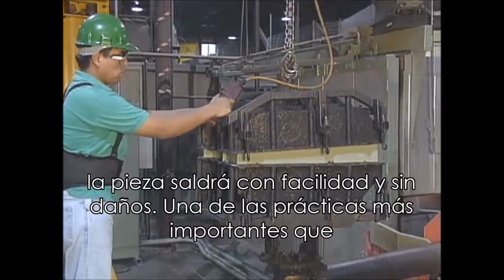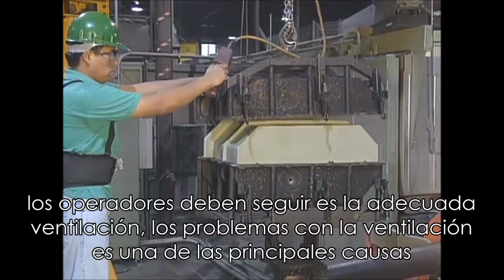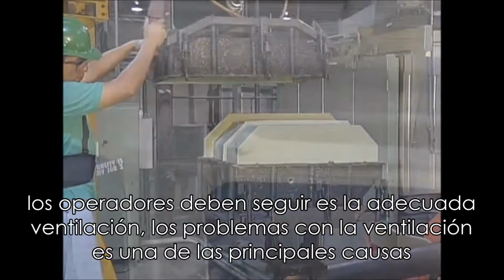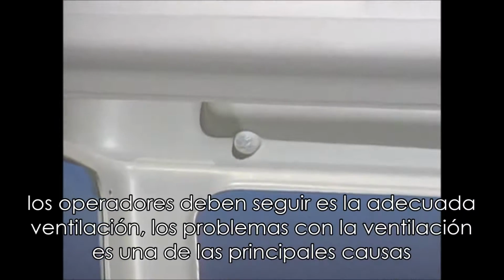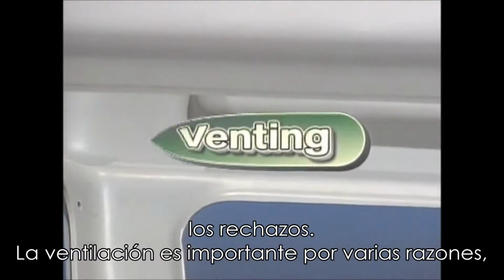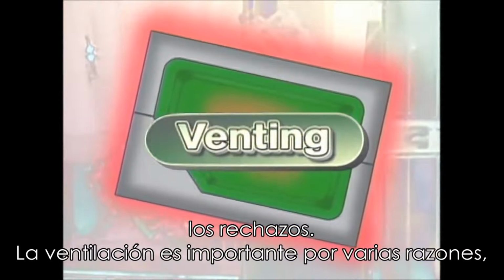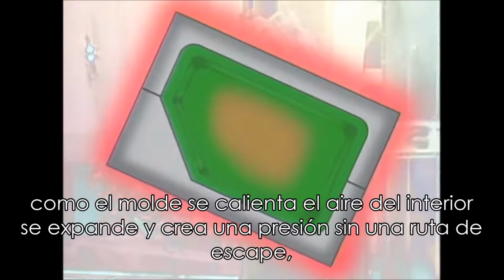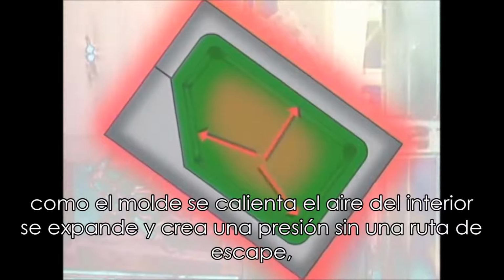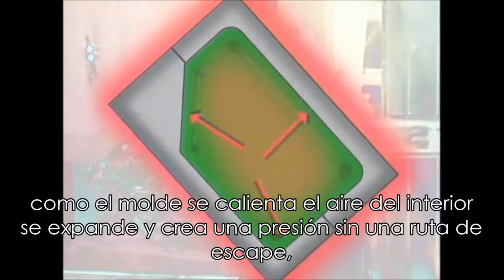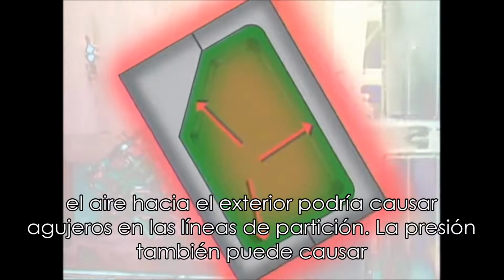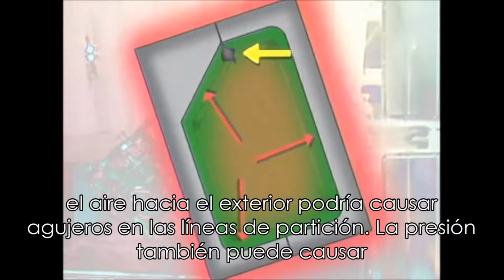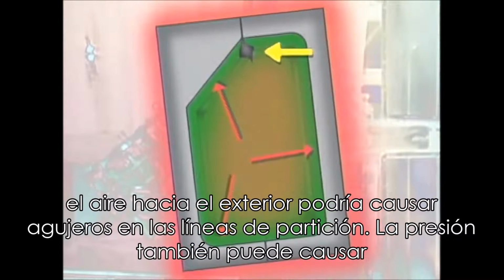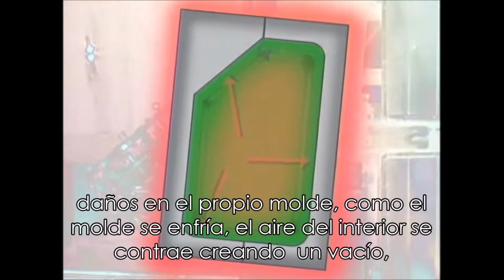One of the most critical practices operators must follow is proper venting. Problems with venting is one of the major causes of rejects. Venting is important for several reasons. As the mold heats up, the air inside expands and creates pressure. Without a path of escape, the air could cause outward blowholes at the parting lines. The pressure can also cause damage to the mold itself.